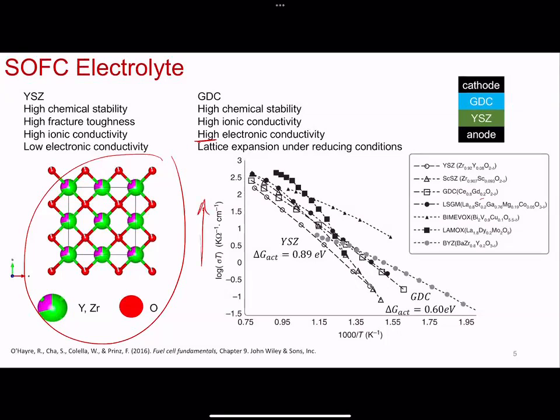here's my ionic conductivity on the y-axis. Here is temperature. So it's actually inverse temperature, so this is an Arrhenius type plot. And so you look at it, you say, okay, well, the activation energy for YSZ, YSZ is right here. GDC is in the square. So it does have higher ionic conductivity, so it's attractive, but the high electronic conductivity limits its use beyond a certain temperature.